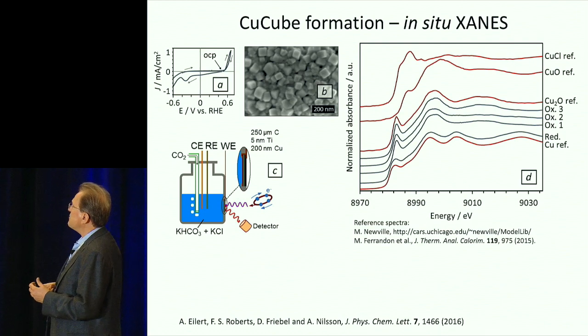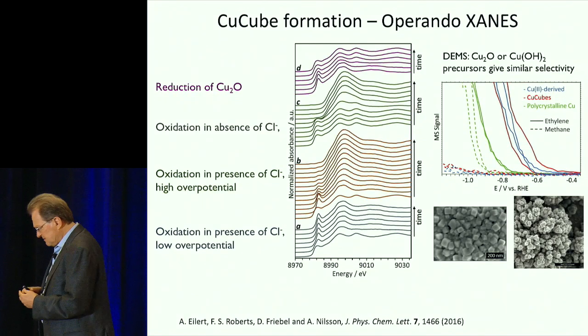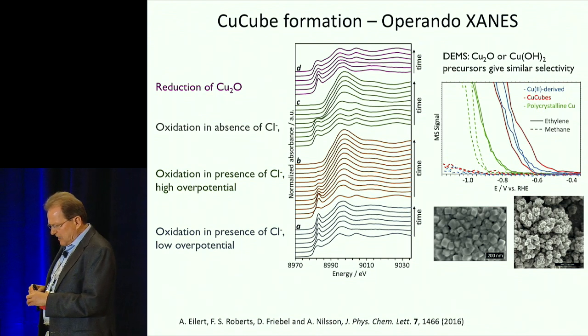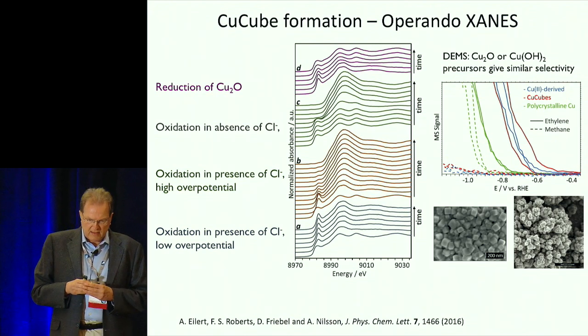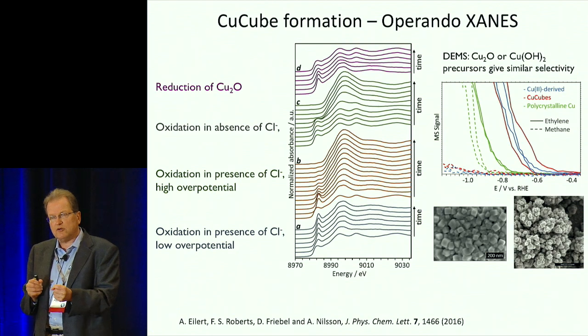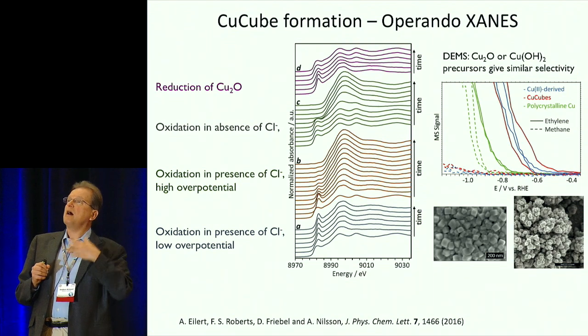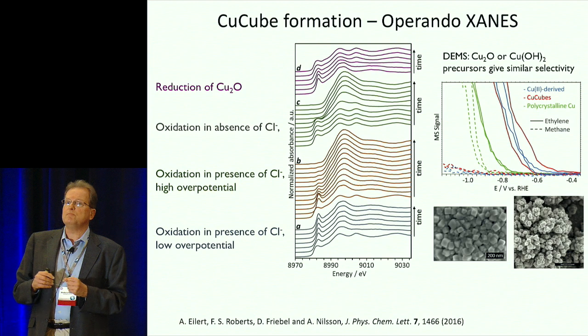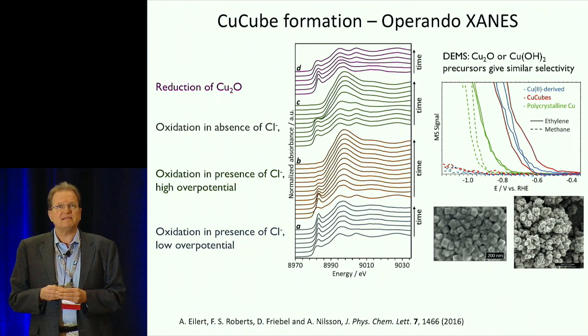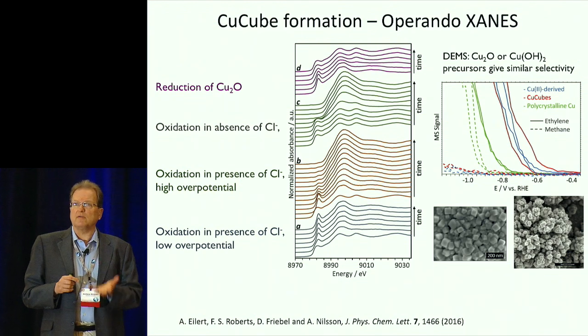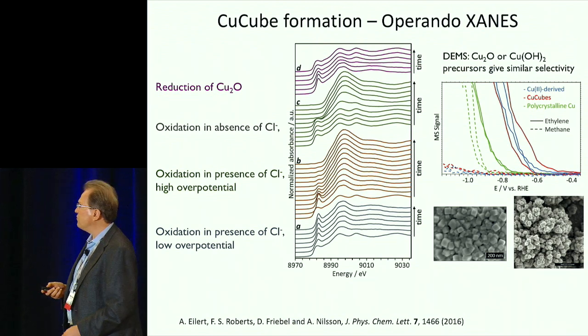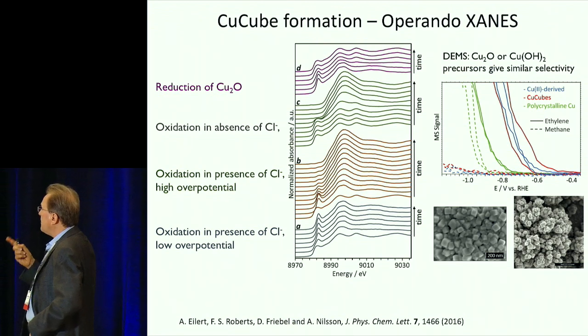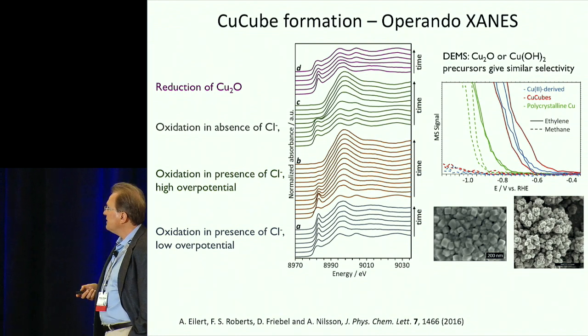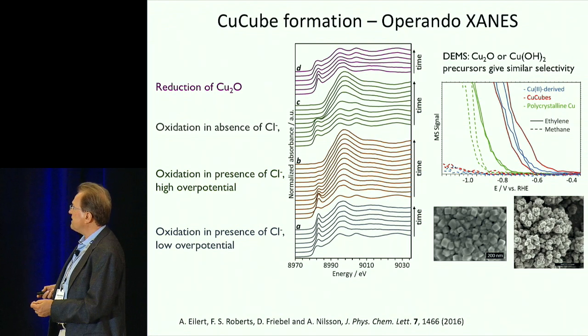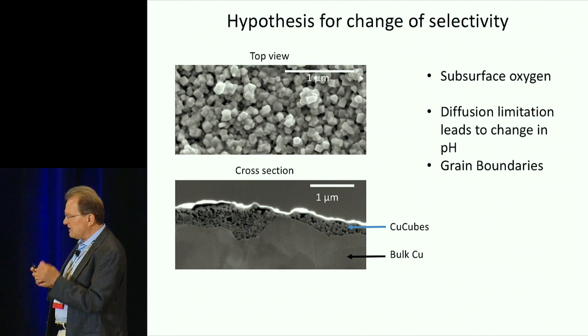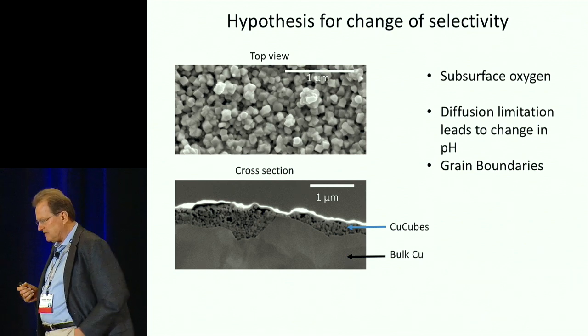And you could actually generate, without going through the details, very similar oxidation without the chlorine present, and then you generate, instead of copper(I) oxide, copper(II) oxide at much higher potential. But as you reduce both of them, you get the same type of selectivity change, with a lot of ethylene compared to methane being formed. And we now also learn that alcohols are being formed here as well, consistent with what Matt Kanan has seen. So one question is, what is making this change in selectivity?